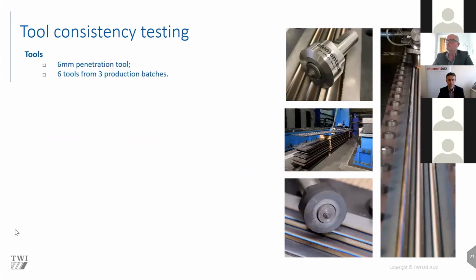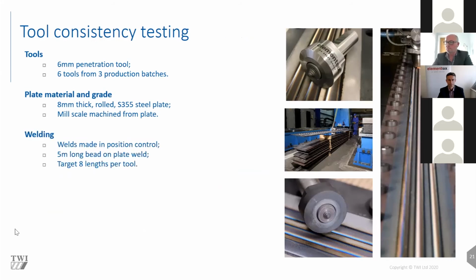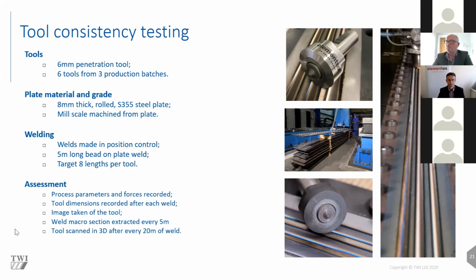To look at the tool consistency testing, we chose one of those cycles, and we decided to look at the 6mm tools that have been developed, and we took 6 tools from 3 different production batches. We tested those welding in S355 steel, which is a standard carbon steel widely used. We machined the mill scale from the surface of the plate to give an identical testing condition for every tool. And then we made the welds in position control, making multiple 5-meter long bead-on-plate welds. And we were targeting 8 lengths per tool to give a total weld per tool of 40 meters.